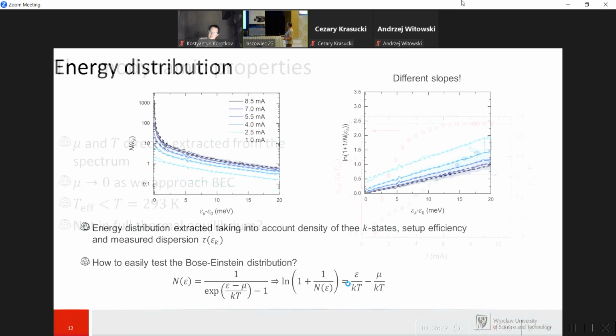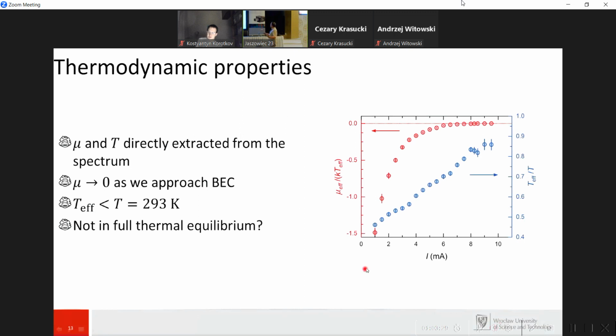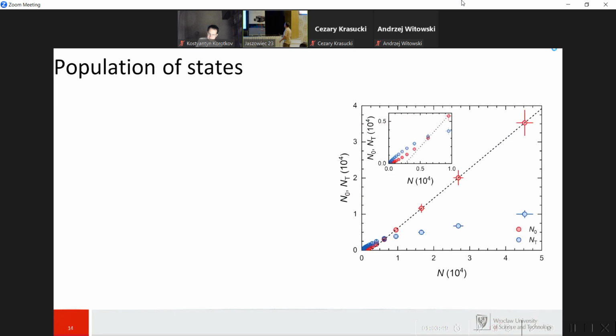So is it in equilibrium? You see the temperatures rise and settle above the condensation threshold to some temperature, and most importantly, it behaves like a BEC, because BEC chemical potential should approach from negative values to 0 as we go to the phase transition. But we hypothesize that it's not in full thermal equilibrium with the gain material.